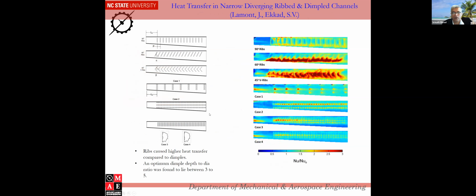This was looking at dimples and concavities in flows, and also ribs, and comparing all this. You have straight ribs, angled ribs, V ribs, then concavities which are put far apart, concavities that are put together, concavities put even closer, to see how the heat transfer enhances. One thing you'll clearly see is the ribs tend to enhance heat transfer significantly, a lot more than concavities. But the only problem is this also enhances pressure drop significantly more than this. So where is the solution in this?